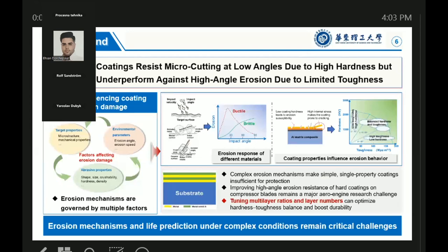However, coatings with high hardness have low toughness, making them vulnerable to high-angle impact. Erosion involves multiple factors, environment, material, and particle properties, so single-layer coatings with simple structures can no longer meet protection requirements. So understanding erosion mechanisms and predicting service life under realistic conditions remain challenging. To address this issue, our study takes a systematic approach from coating design and preparation to performance testing and finally to erosion mechanical load coupling analysis.